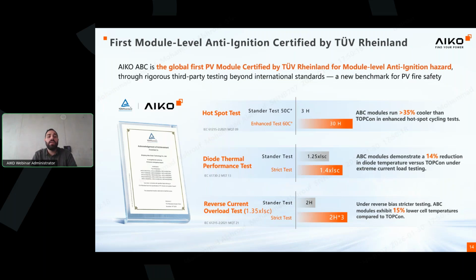And the third one is the reverse current overloading test, where the standard test applies 1.35 of the short circuit current for 2 hours. We did it for a longer time, basically 6 hours, 3 times the standard time. The result showed 15% lower cell temperature. So you can see in the three tests, we always show lower temperature. As a result, our panels were defined as anti-ignition panels, and this is the first module worldwide to have this certificate.